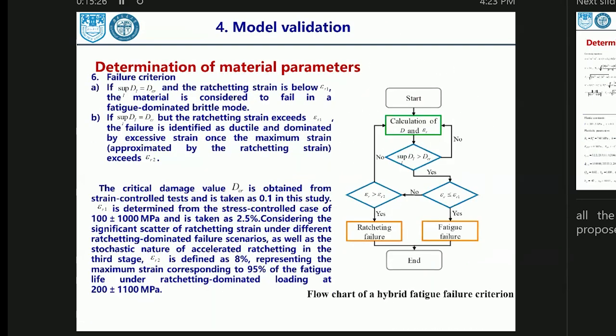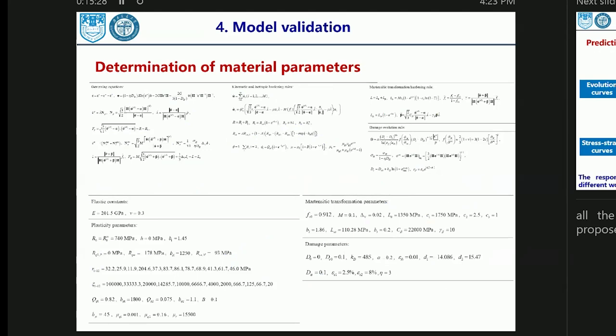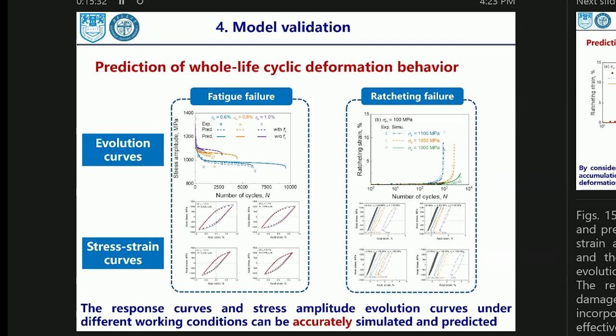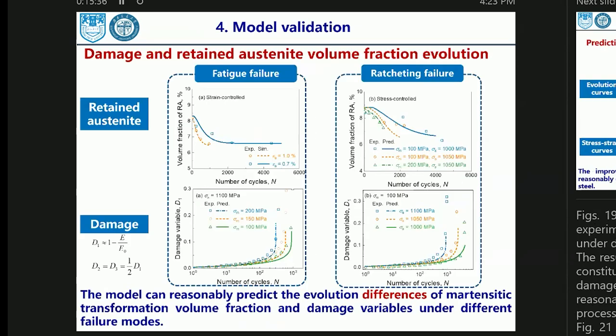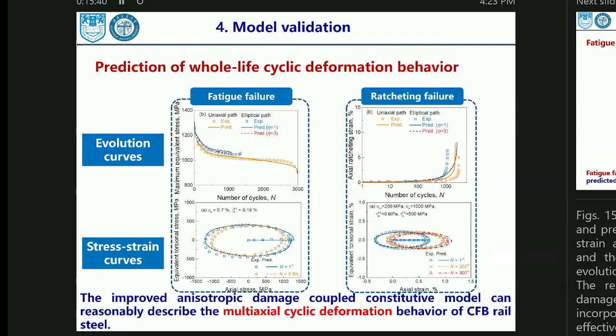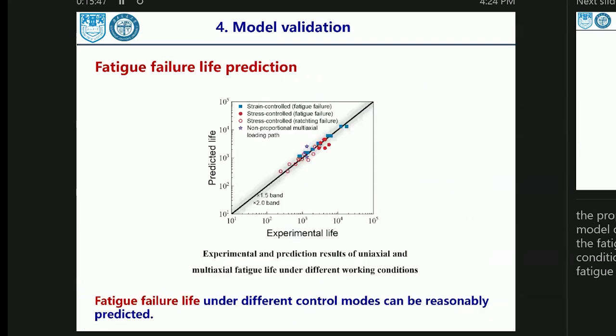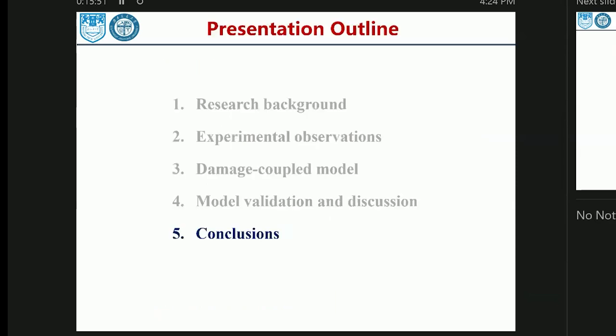And these are the material parameters used in this model, and the results show that our model gives a good prediction compared with the experimental ones. Not only the strain curves, but also the whole life evolution curves and the fatigue life can be predicted well.